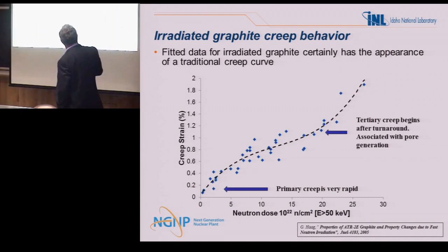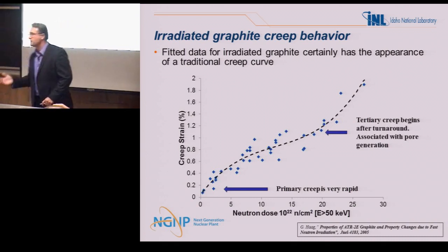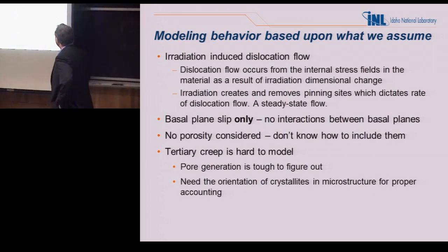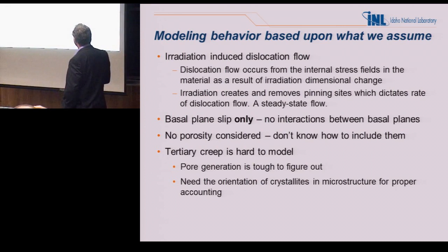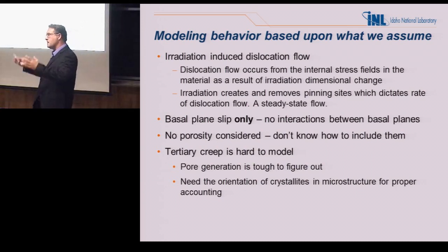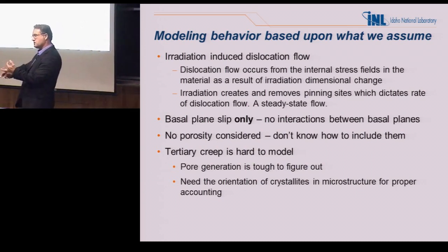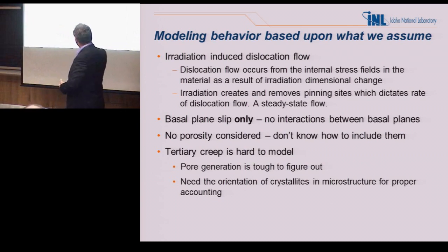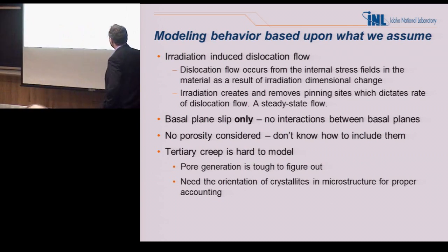Okay. Basically, the primary creep is very rapid. It's almost immediate. Tertiary creep begins after turnaround. It's associated with pore formation. Thinking we knew what we were talking about, we came up with a model saying, all right, we understand what's going on. We've got a radiation-induced dislocation flow. The dislocation flows because of the radiation removing any pinning sites, allowing dislocation to move. It's a function of the temperature. It's a function of the flux. Therefore, we kind of understand what's going on.